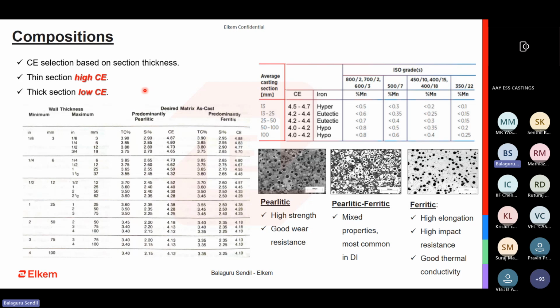I would like to highlight here that when you are going for high silicon grades, you have to be very careful. High silicon means SSF kind of grades. You have to be very careful with respect to your FeSiMg or nodularization as well as inoculation. The silicon is already high. If you add an overdosage, then you might end up getting a lot of shrinkage related issues, a lot of carbides and very poor mechanical properties, or the casting would be extremely difficult to machine.